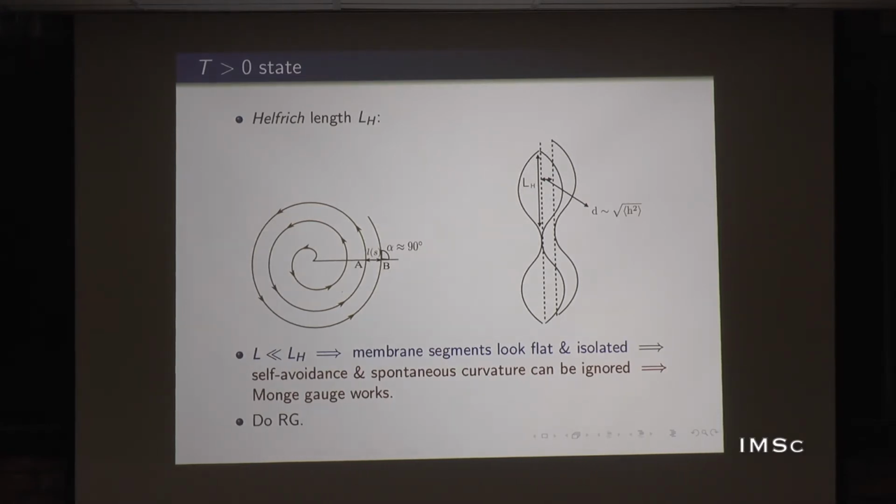which will make the members of the stack fluctuate. But as soon as you raise the temperature, the individual members of the stack will basically start to wiggle like this, then basically touch occasionally here and here. They will basically hit each other at some typical distances. Because of these random hits, which are essentially due to the thermal fluctuation, the individual members of the stack will try to expand. So, essentially thermal fluctuation creates an effective repulsive interaction in a stack, which is called the Helfrich interaction.